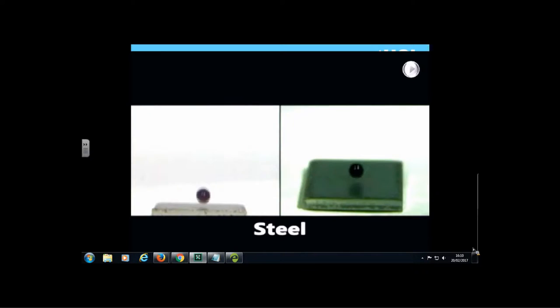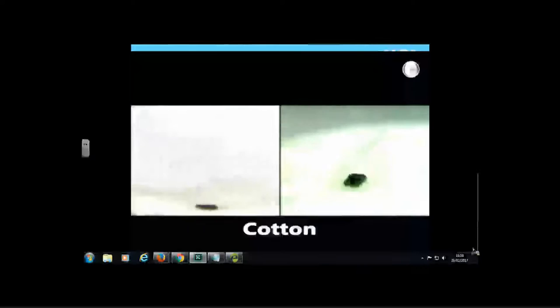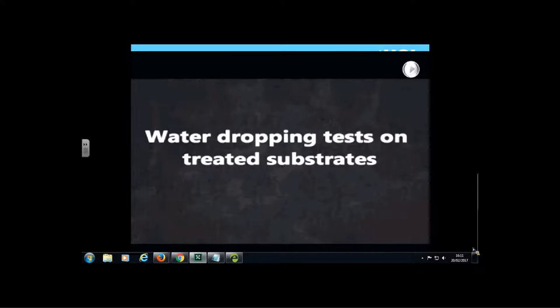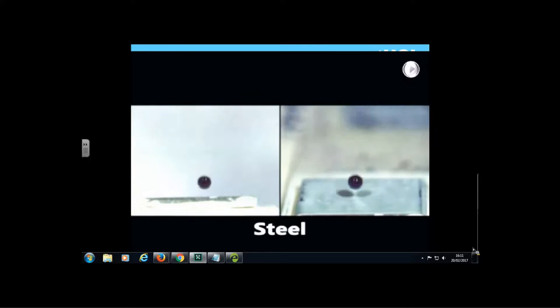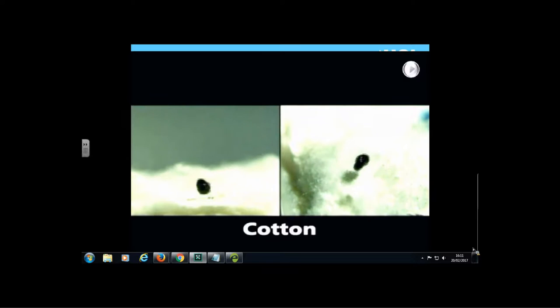This video shows coatings not treated with a superhydrophobic surface: water droplets dropped onto cotton, paper, and steel surfaces simply splat onto the surface. However, if superhydrophobic, the surface is very water-repellent and the water droplet — in this case dyed with methylene blue — bounces on the surface. Even cotton, which can absorb the force of a dropped water droplet, will bounce on these superhydrophobic surfaces. This is achieved using dual-scale roughness of different nanoparticles combined with an adhesive backing layer.